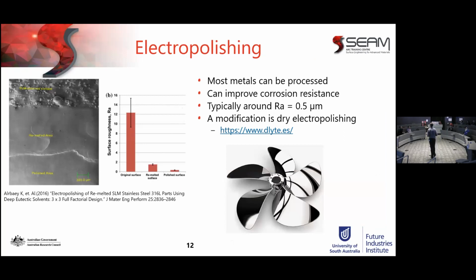Electro polishing. So most metals can be electro polished, nice and simple. Hook it up to a power supply, dip it in a liquid, and it can create nice smooth surfaces. And there are refinements to that where you can do dry electro polishing basically with a conductive medium. You drag your part through this hard particulate conductive medium. So you've got abrasion, but then on impingement you've got an electric discharge. So you've got both electrical discharge machining as well as mechanical wear going on. And that combined can create a very smooth surface. It's the refinement of electro polishing.